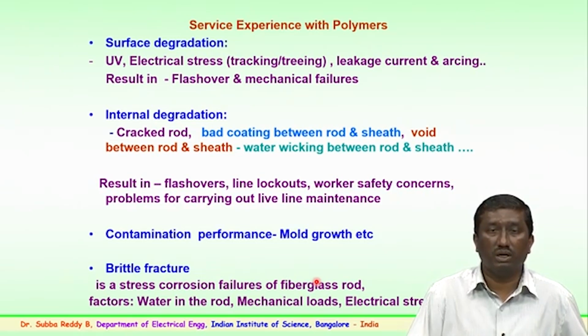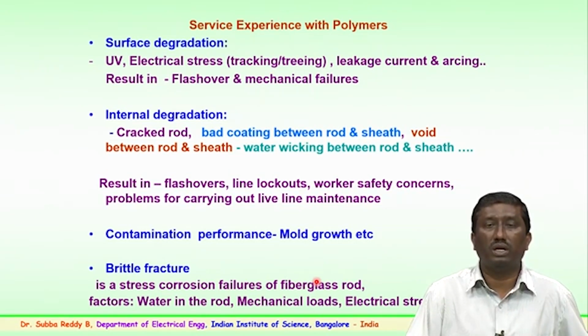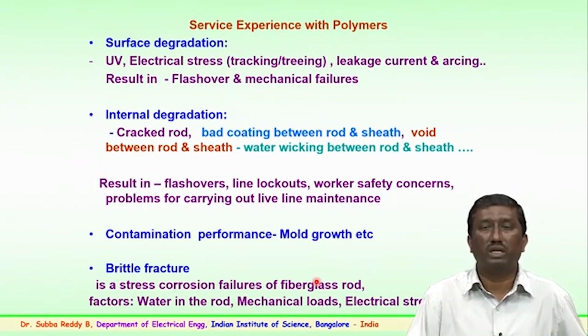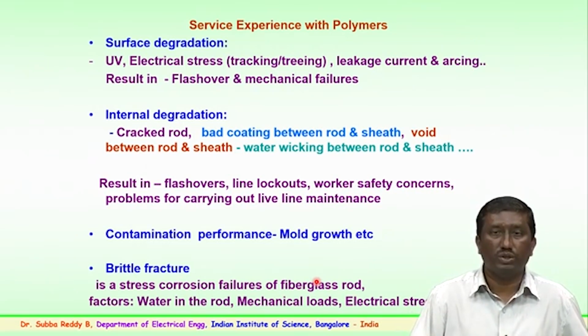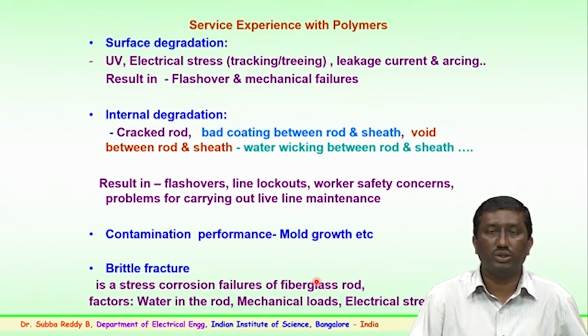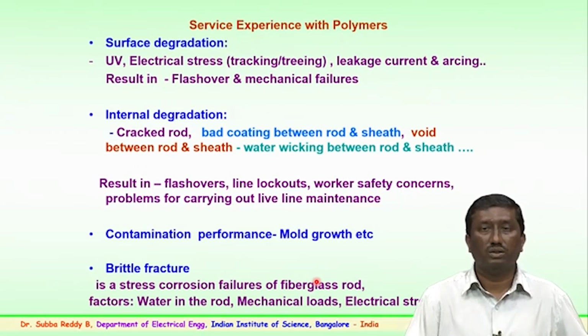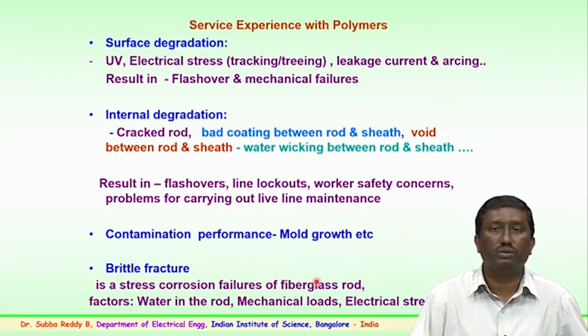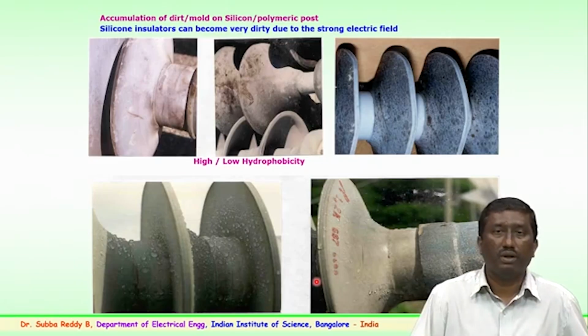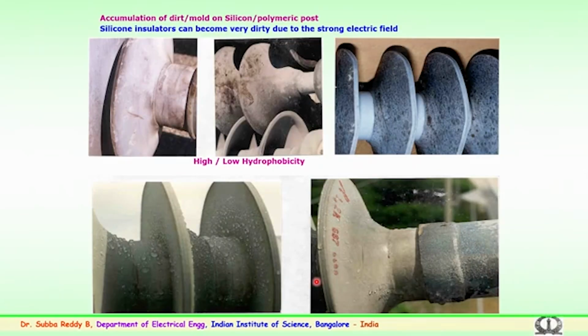And brittle fracture. Again, I was mentioning brittle fracture: this is a stress which happens on the fiberglass rod, or a corrosion failure of the fiberglass rod. Factors could be water entering into the rod because of mechanical load and electrical stresses, and the formation of nitric acid because of this moisture, which over a period of time could lead to the fiberglass rod becoming brittle and fracturing. A few of the experiments we have carried out in the laboratory, we will demonstrate in the future slides.